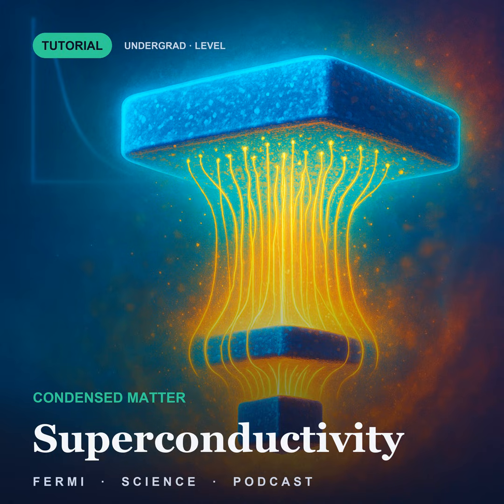Put a coupling of 1/4 into that, and the exponential gives you about 1/50th. Take a phonon energy scale of a few hundred Kelvin, and you land on a transition temperature of a few Kelvin. The 10,000th we could not account for is manufactured, entirely, by that exponential. Not by any small quantity in the metal, but by the fact that the answer is non-analytic in the coupling, which is also precisely why nobody found it by expanding in powers of anything.